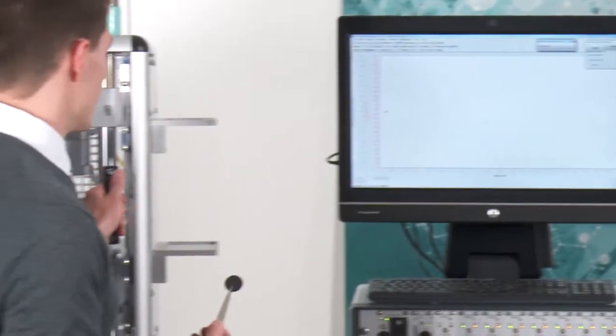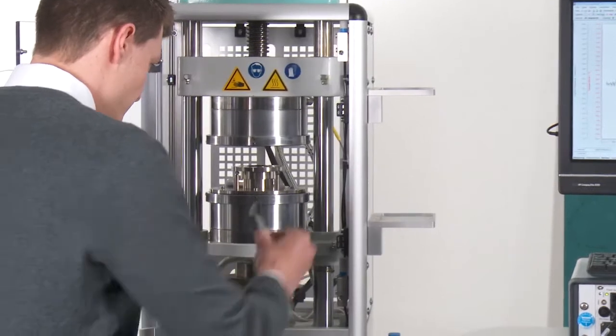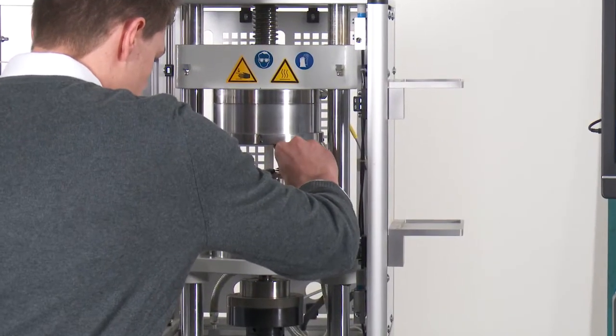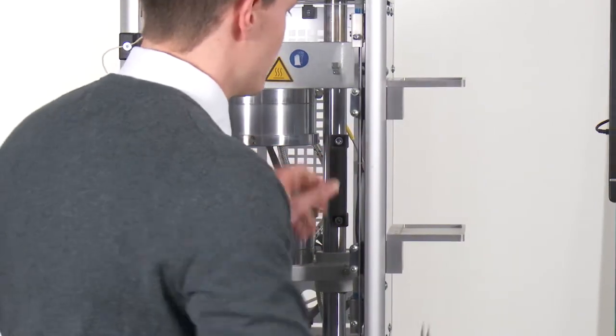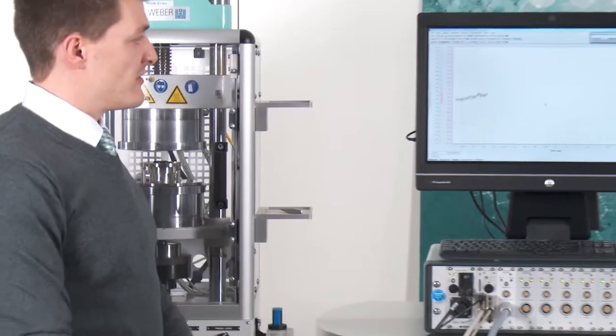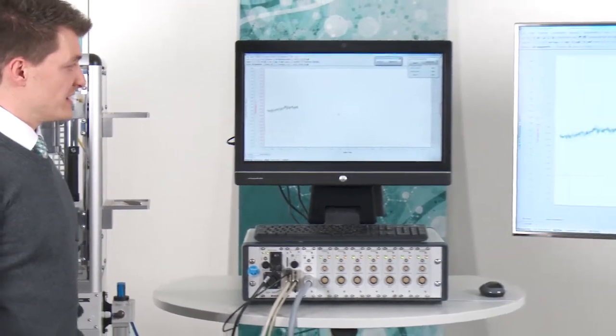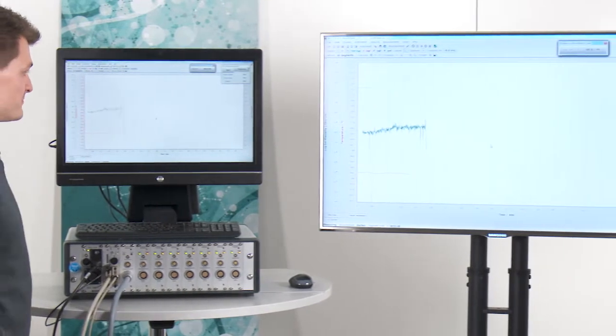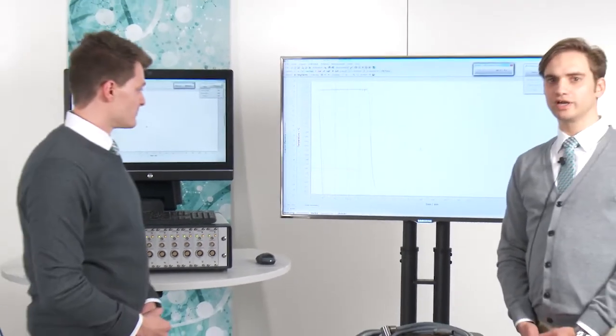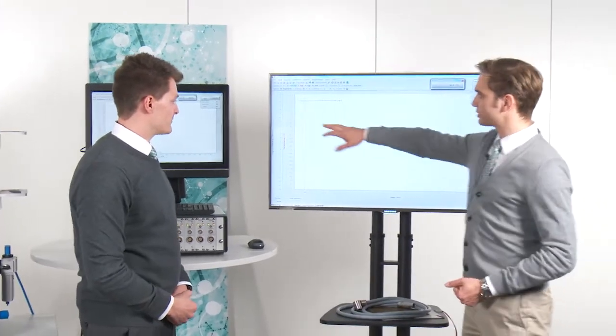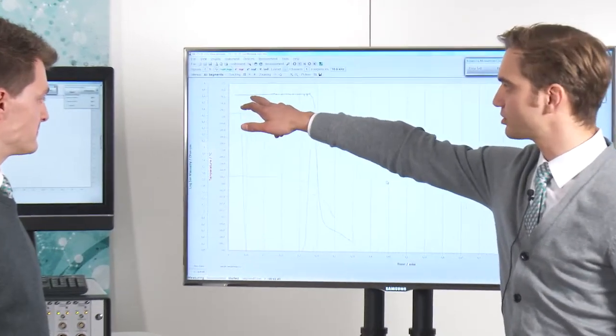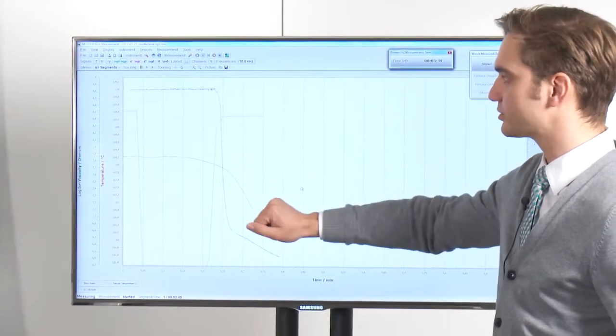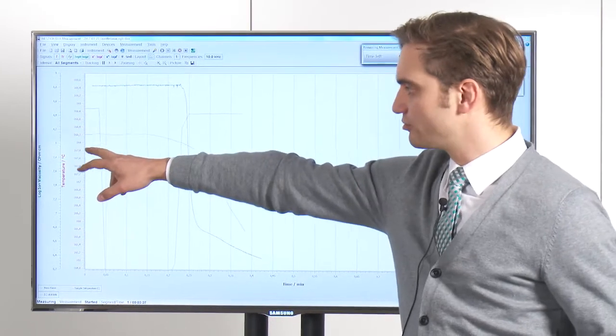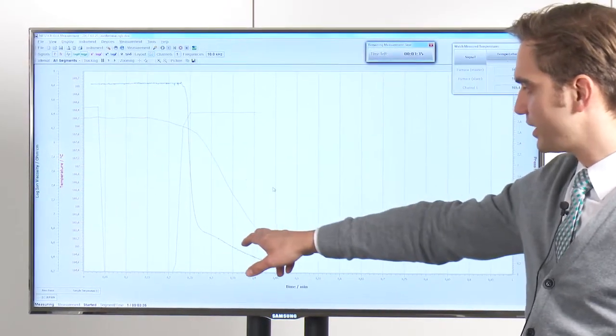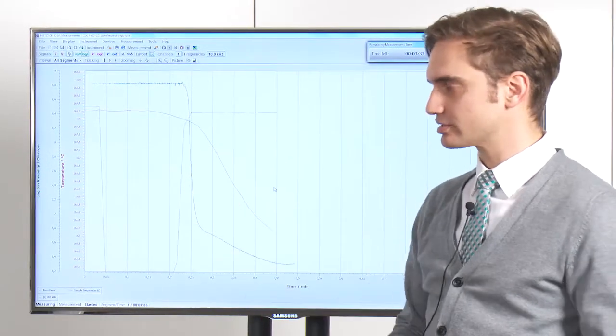So now I'm using this carbon fiber prepreg material. Open the door, put the material into the mold, close the door, and we will have a look at what is happening now. Okay, we see that something is happening already. We have a look at this green signal here. Well, you see the green curve. This is nothing else but the dielectric signal. Also, we see a red curve here that is tracing the temperature as it occurs.